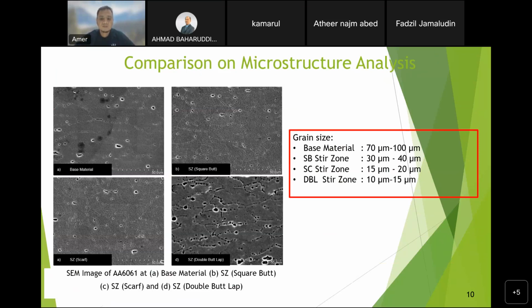And for the scarf, the average size is 15 micrometer to 20 micrometer. And the last one is the double butt lap joint microstructure. The size is 10 micrometer to 15 micrometer. So the smallest grain size is in the double butt lap joint. You can see the big gap between it and the other joints.